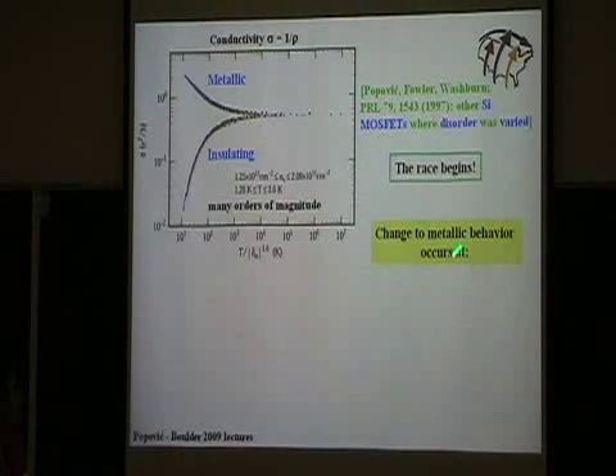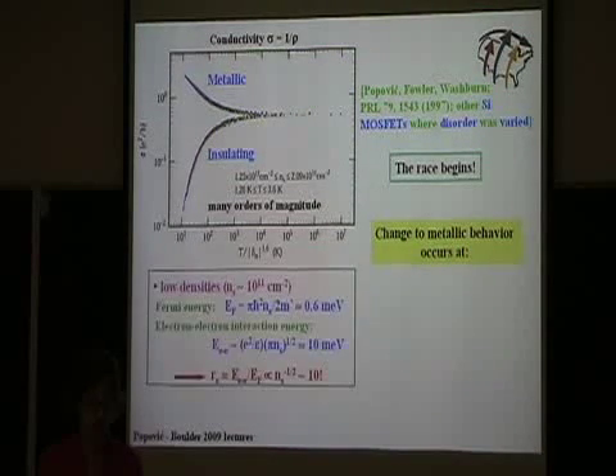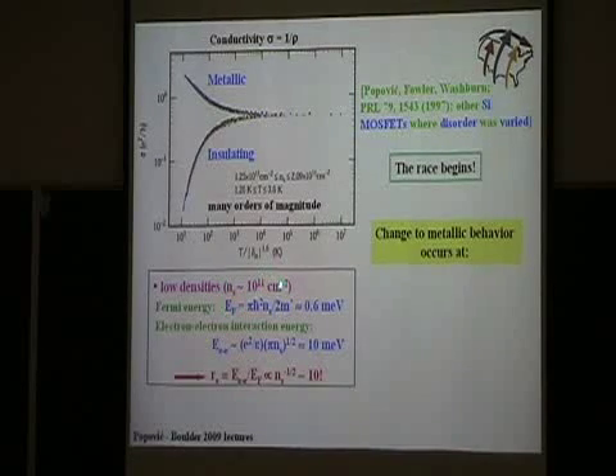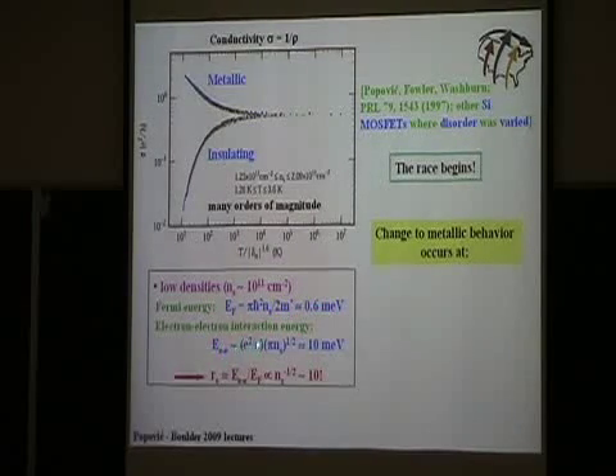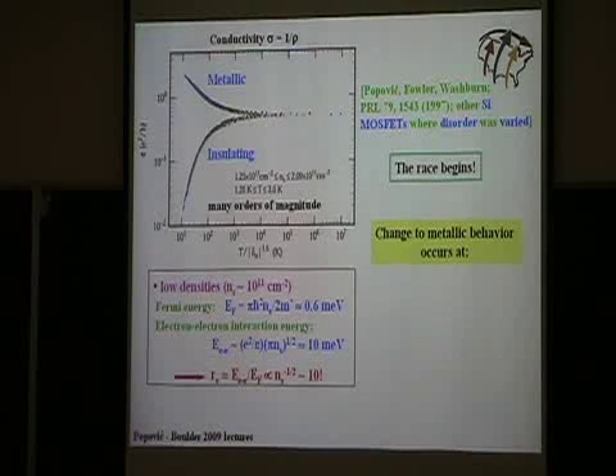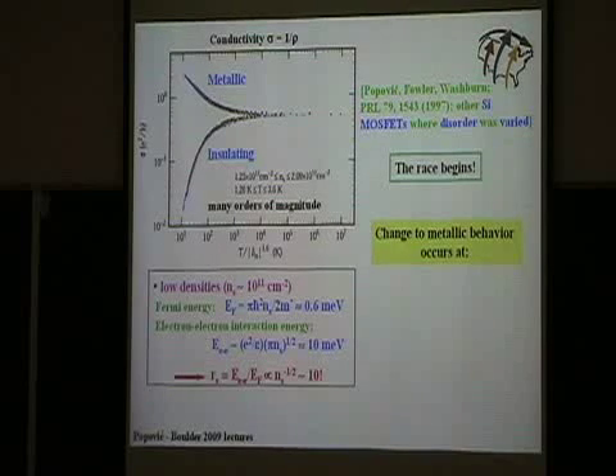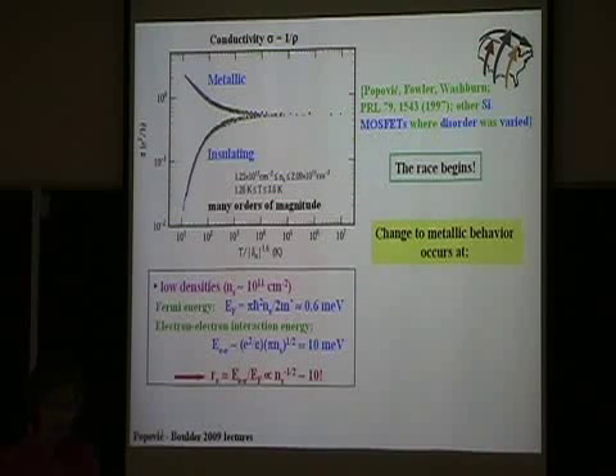So what I want to point out now is that the change from the insulating to the metallic behavior occurs at relatively low densities, which are typically of the order 10^11 per centimeter squared. And you can estimate the Fermi energy easily. And also, you can estimate the Coulomb energy. We know everything here. So what we see is that the Coulomb energy is much larger than the kinetic energy by at least a factor of 10. In other words, the interactions are very strong. You cannot treat this as a non-interacting or weakly interacting system. The interactions have to be taken into account.